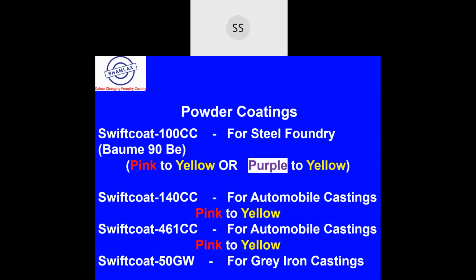Similarly, the Swift coat 50 GW will be a graphite based coating for the gray iron castings, and you can have a Baume of around 55 to 60. It will again be a water based coating. If you are using RFU coatings, then we have the RFU coatings, which will have a Baume of around 90 in the case of steel foundry zircon based coatings.